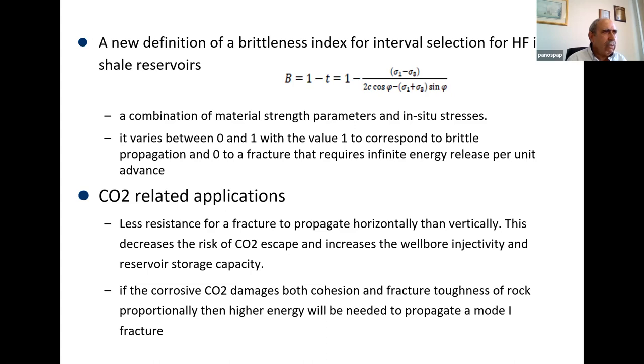From Fushen Liu: in your experience, how large may the plastic dissipation be in terms of the energy budget compared with elastic potential energy, fracture surface energy, and the fluid viscous dissipation zone? As I showed, the measure for me of the energy dissipation was the effective fracture toughness, the elevated fracture toughness, which I calculated. This is the measure of the dissipation of the energy.